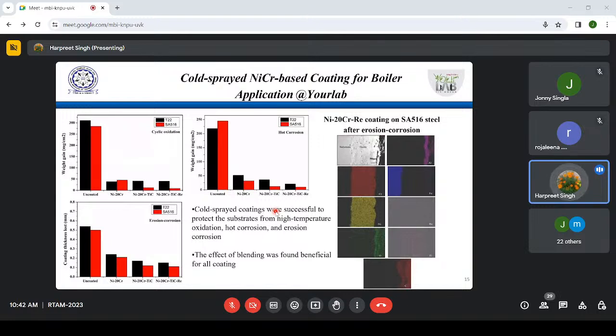Now then comes some of the applications. So we have seen most of the fundamental things, but then the capabilities. I'm showing you some of the case studies here, again done here. So this is a nickel chromium based coating. Here we have added 25% titanium carbide in these coatings. You can see these are composite coatings which we developed very nicely, and we could see that they were giving us very good erosion corrosion resistance. Very good, in fact. These additions were helping us to get better and better properties.